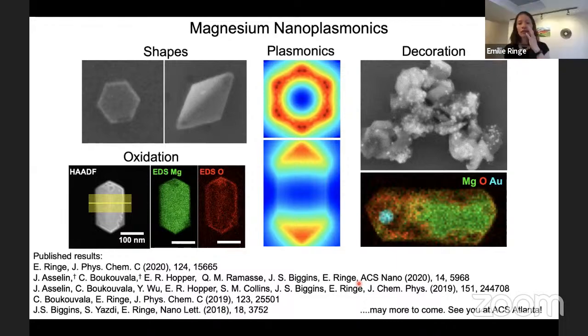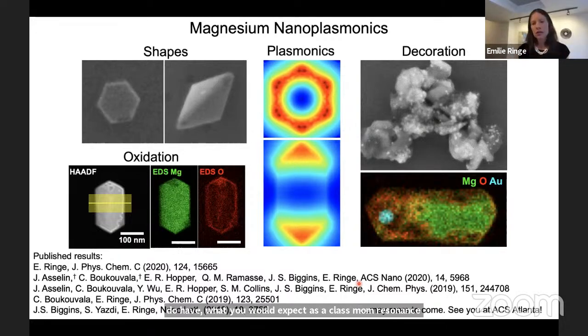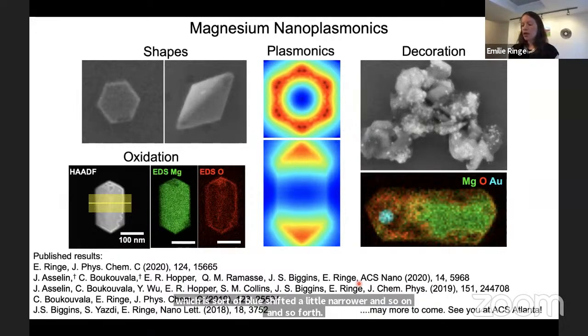Oh, smaller. Oh, we've absolutely cracked that nut. I've not shown these results, but basically by changing the overall concentration of everything in the solution and the reaction temperature, we can actually get structures down to about 50 nanometers. Which do have what you would expect as a plasmon resonance, which is sort of blue shifted, a little narrower, and so on and so forth. So no, there are no real limitations at the moment.